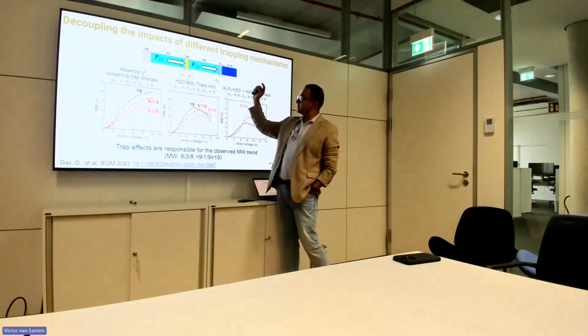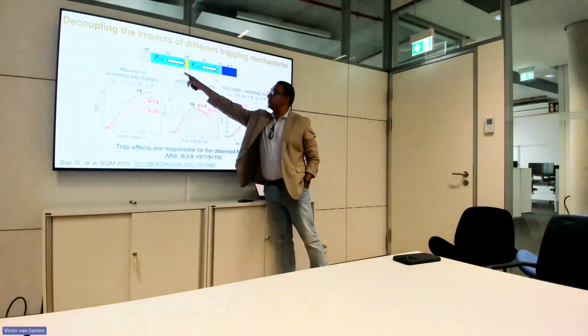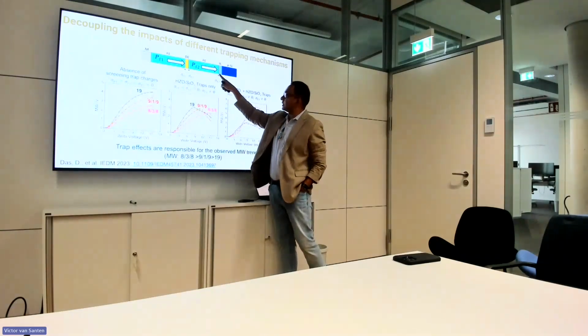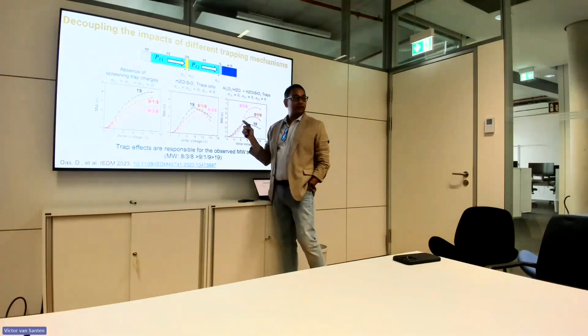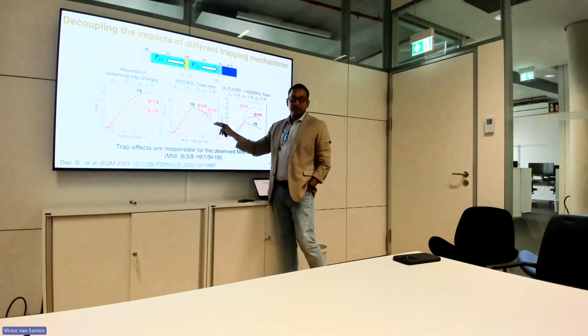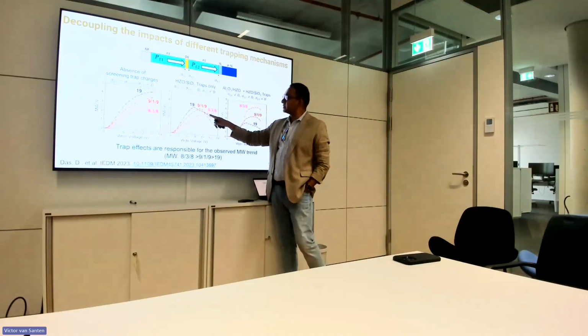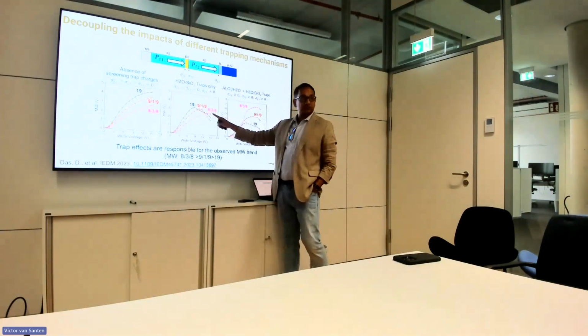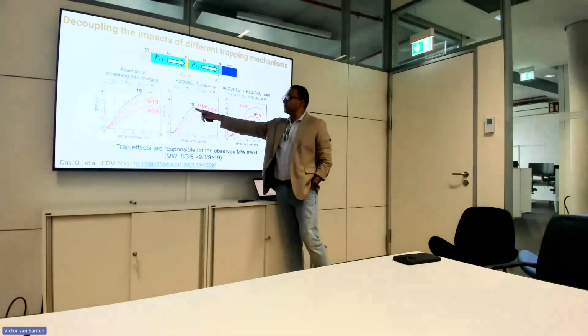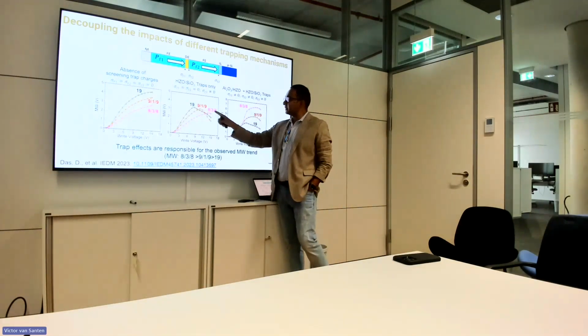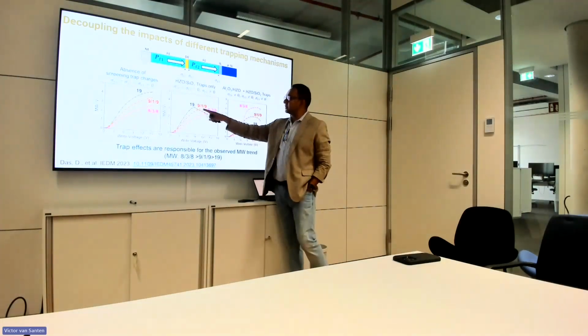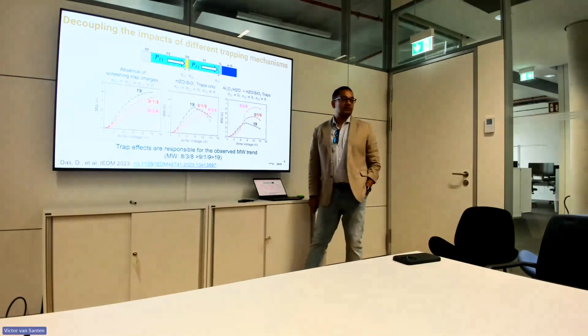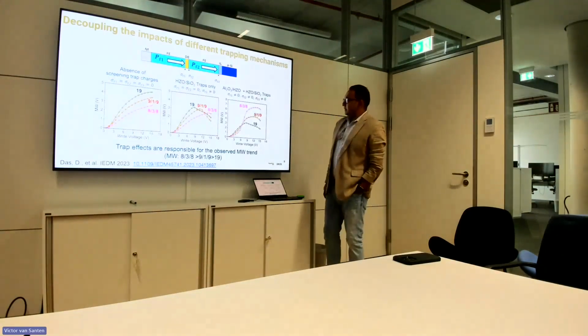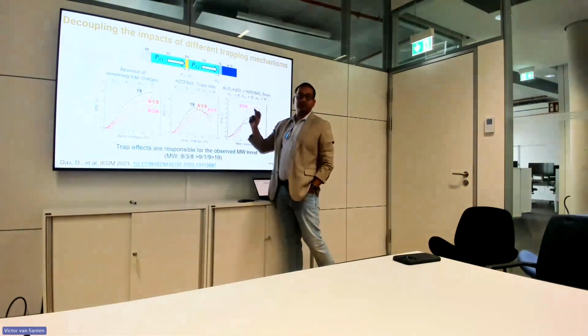Okay. So next, we introduce that maybe the traps over here are 0, but we still have traps over here. And in that case, we get a better prediction in the simulation results, meaning that the maximum memory windows are of similar characteristics. And importantly, we see that there is a peak memory window and then it goes down. Okay. So we see those characteristics, but quantitatively, it is still not picking up the experimental trend, where 3 nanometer alumina has the maximum memory window. In the last case, what we did is we introduced traps at all the interfaces.